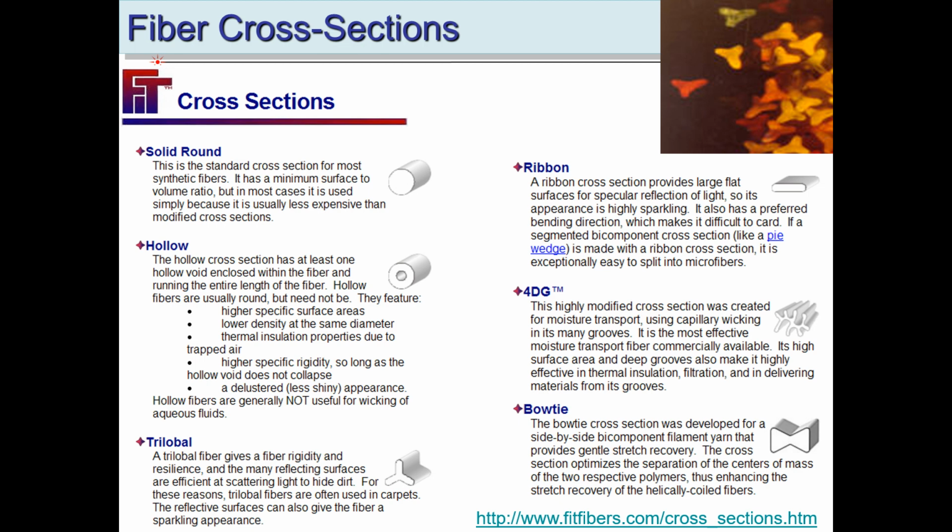Chemically, if you put that on an FTIR and squeeze it, polyethylene, say, you put that on an FTIR, polyethylene, you're a chemist, and you say they're the same fiber, but you never used a microscope. So you're totally screwed up. All you had to do was look at the cross-section and say, these are not the same. They're made out of the same polymer, but there's more to it than just the chemical properties. There's the physical properties that you need to look at. And so, saying this is chemically the same as that is one thing. That might tell you it's the same company, but those shapes under a microscope would look completely different.